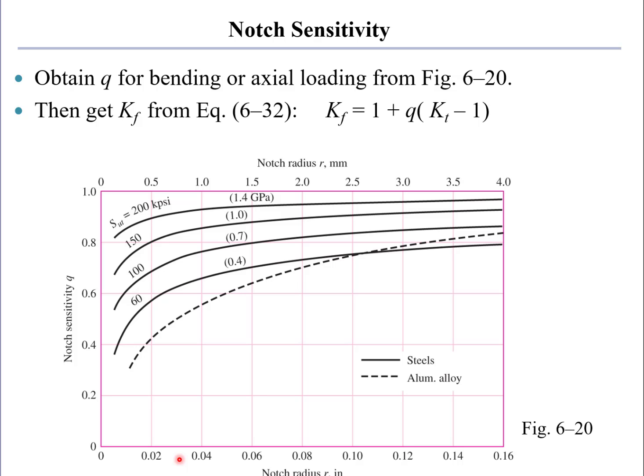And there are tables that can be used that plot the notch sensitivity against the notch root radius. So the notch root radius, in effect, sets a probed volume size where you could be nucleating fatigue cracks during fatigue loading. And the notch sensitivity curves are parameterized by the ultimate tensile strength. You'll notice that as the ultimate tensile strength goes up, the notch sensitivity, in fact, goes up. Higher strength, higher notch sensitivity. We take this fatigue stress concentration factor equation for any given R and a known ultimate tensile strength, we read off the notch sensitivity. As you can imagine, that is a nuisance.